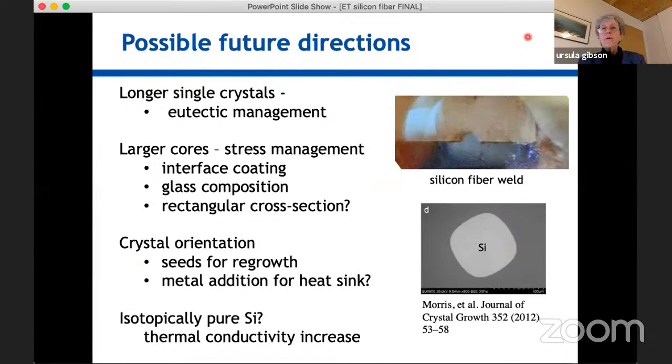Okay, if I were going to make a hollow silicon fiber, I do think it's possible in a couple of different ways. One thing you could try to do is to put something into your preform that would get dragged down along with the fiber, and then that would be sacrificial. You could etch it away later. It's a little tricky to really know whether we could just put a rod of SiO2 down the middle and have that follow down the fiber. I think that would be unstable.